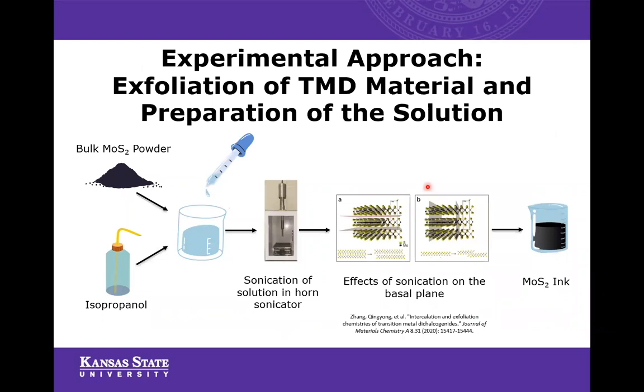So moving on to the preparation, making fibers containing nanosheets of TMD materials is a multi-step process, and step one includes exfoliation of such TMD material. The TMDs are available in bulk powder form, which has to be mixed with a solvent such as isopropanol and sonicated with a horn sonicator. The tip of the horn sonicator generates ultrasound, which creates cavitation with high kinetic energy or surface energy, which peels off individual layers of sheets of TMDs. Here you can see the action in the picture.